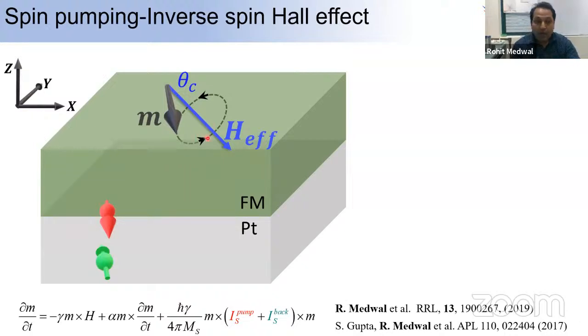But to allow these magnetizations to persist, we apply an external magnetic field, HRF, orthogonal to this, which will pump the magnetization and allow it to have sustained precession about the external magnetic field. This is how we excite these magnetizations to persist about the external magnetic field. And theta c is the precession cone angle, the angle at which this is persisting.